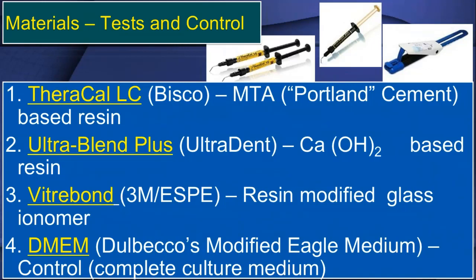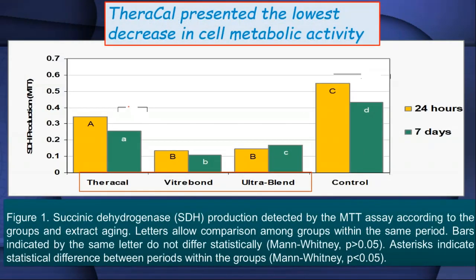So he looked at TheraCal LC, UltraBlend Plus, Vitrebond, and of course the Dulbecco's modified Eagle medium, which is the cell culture medium. It's what you grow these cells in. And that's considered your control, okay? So that's your control right there. And what he found was really fascinating because TheraCal by far represented the lowest decrease in cell metabolic activity. And they do this by measuring the health of the mitochondria. All my research I do with mitochondria, so it's very exciting to see research like this for dentistry. Basically they looked at the level of succinate dehydrogenase production. They said, wow, these cells are actually fairly healthy. They're not growing badly at all, much better than Vitrebond, which is, you know, cytotoxic.